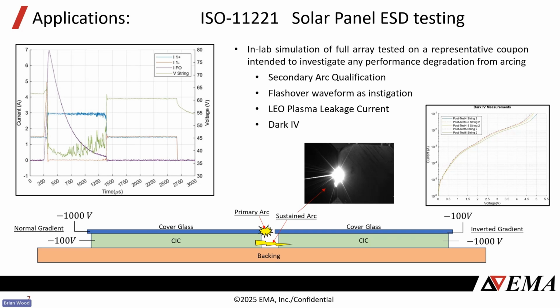And this is becoming more of a concern with the electric propulsion movement that's going now, where we're trying to maximize the weight to fuel ratio. And so people are doing these slow orbit raisings with these plasma thrusters, which is a good idea, but it can also provide additional contamination or plasma ambient to the spacecraft, and can enhance that leakage current issue. And so that's something that we're also able to investigate.